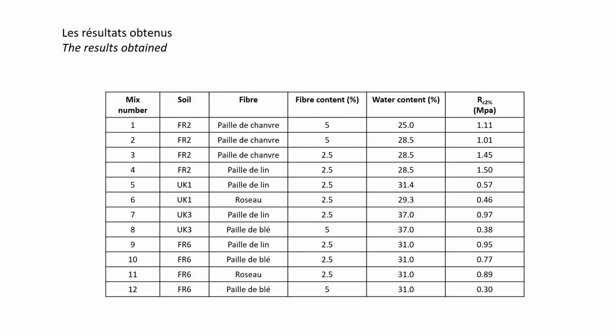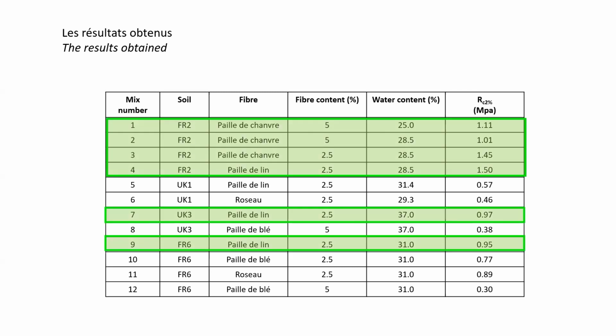So here you can see some of the results highlighted. And you've got some mixes using flax straw or hemp straw that gave us compressive strength results that were quite positive, close to or above 1 megapascal for a concentration of 2%. So these results were quite interesting, whereas wheat straw or reed straw, which was interesting theoretically, in the mix with some soil gave us weak results compared to hemp and flax straw.